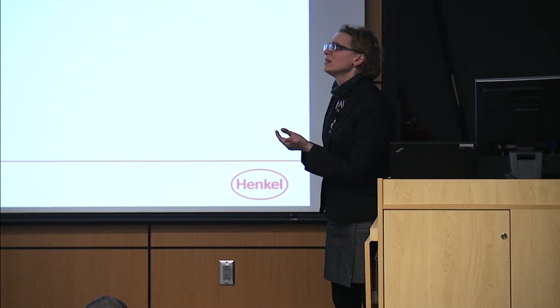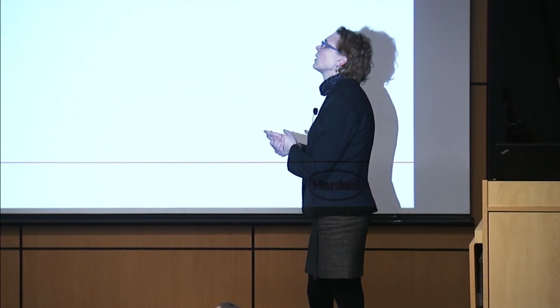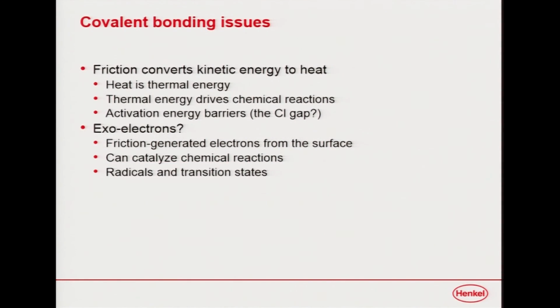So what happens to get a covalent bond? Well, you need a lot of heat, and friction, thankfully, generates a lot of heat. I'm sure you've all heard people say, you know, check your brakes and make sure you didn't get them too hot when you're going down a hill. Don't ride your brakes going down the hill. Well, that's because friction generates a lot of heat, and if you cook your brake linings and you cook your brake rotor, they won't work anymore. Why? Because they've changed chemically. So you no longer have the same frictive interface, and it doesn't work. Thermal energy drives chemical interactions.